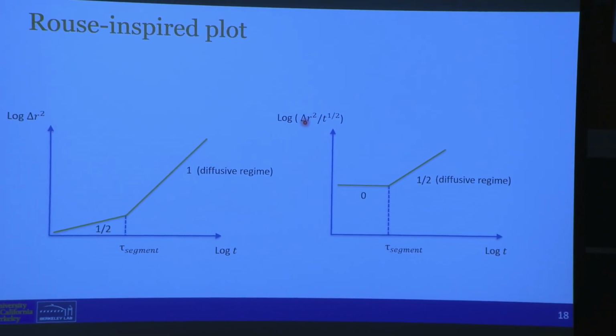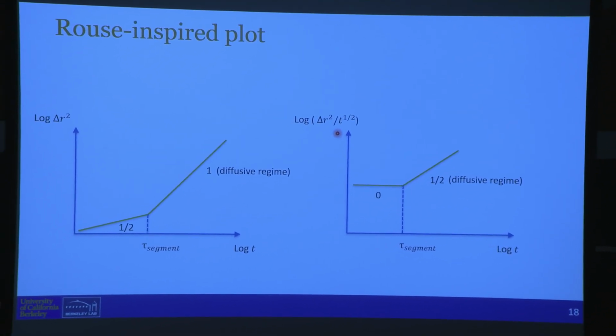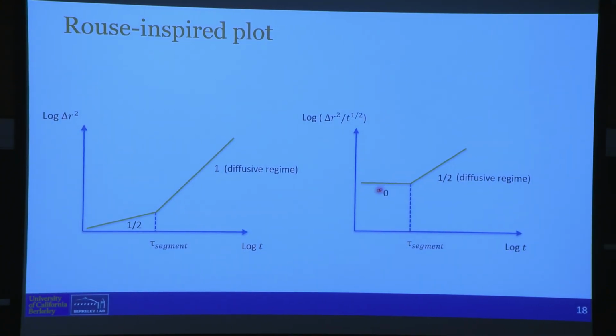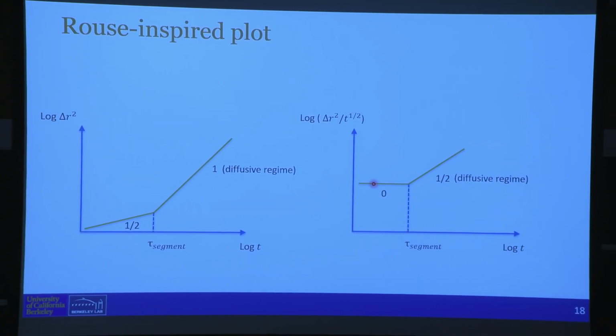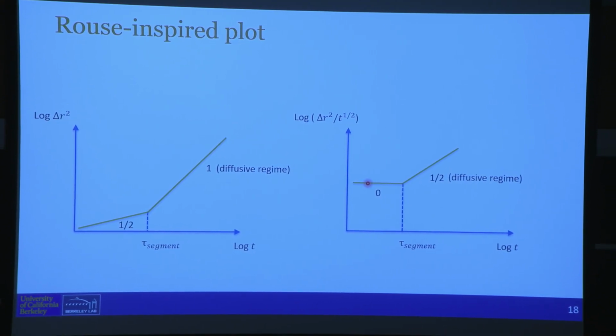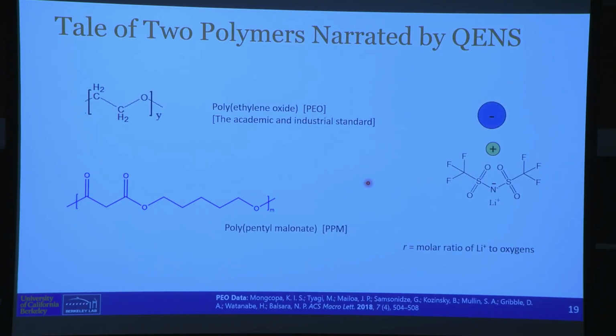When I measure delta R squared, I'm going to normalize by t to the half so that I get a plateau of 0, so that then I can see what else is there in the system, because that's what we expect as polymer scientists. We expect Rouse to be correct. You can take neutron scattering data on these two systems, and then look at it as a function of this r, the salt concentration.